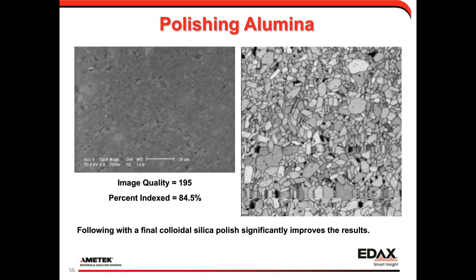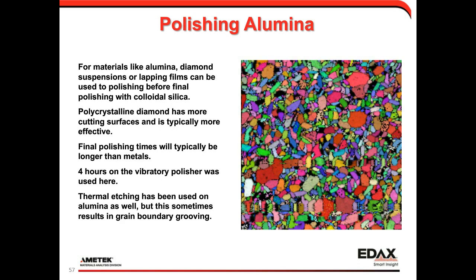But now if we take our alumina result and then polish it with colloidal silica, so we're not only polishing but also using a little bit of a chemical etch, you see that our surface becomes quite a bit flatter, and we get an improvement in indexing rate to about 85%, in a sample that has some pores in it as well. You can see we can start to see the microstructure. Generally, for hard materials like alumina, I'll use something like a diamond suspension or a lapping film to polish before the final polishing with colloidal silica.